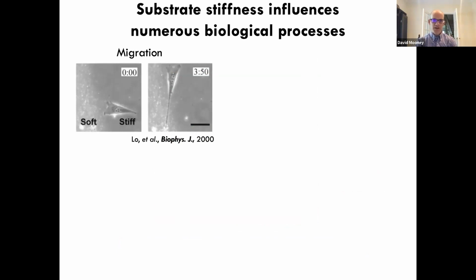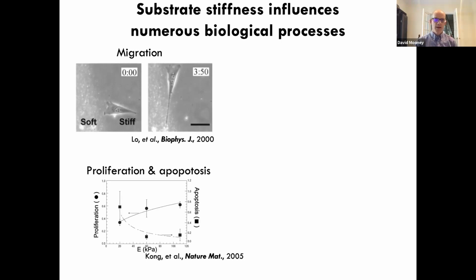And actually, Yuli Wang at UMass, I think, had the first really significant demonstration that indeed cells did respond to the stiffness of the materials that they encountered and adhered. He showed that the migration of cells was dramatically impacted by the stiffness of the substrate. Jun Kong, actually in the lab when we were back at the University of Michigan, demonstrated that the proliferation and cell death was regulated by the stiffness of the substrate.